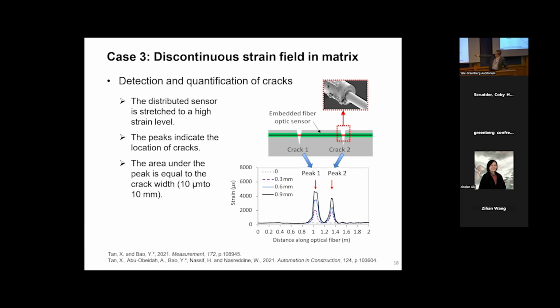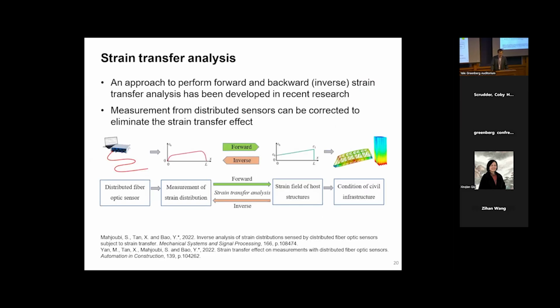If you look at this plot, the horizontal axis is the distance along the fiber. The vertical axis is the strain, so we can map the strain distribution along the sensor. By looking at the sensor signal, we will know if there's a crack or if there are multiple cracks, and if there's a crack, what is the location and what is the crack width. So based on this understanding, we developed a two-way strain transfer analysis. Basically, we were able to convert the measurements from the sensor to the real strain field condition, meaning that if you deploy a fiber optic cable in a structure like a concrete block, then from the readings of the sensor, you can accurately determine the strain distributions, and similarly, you can determine temperature distributions.